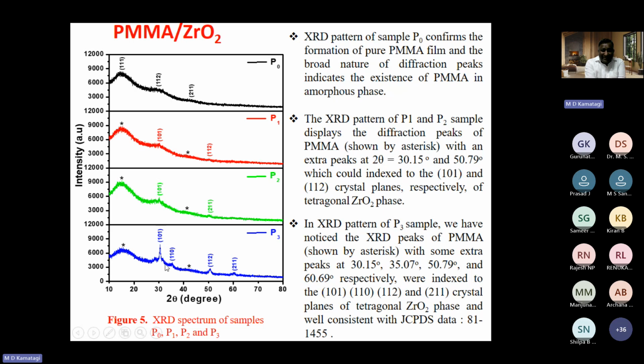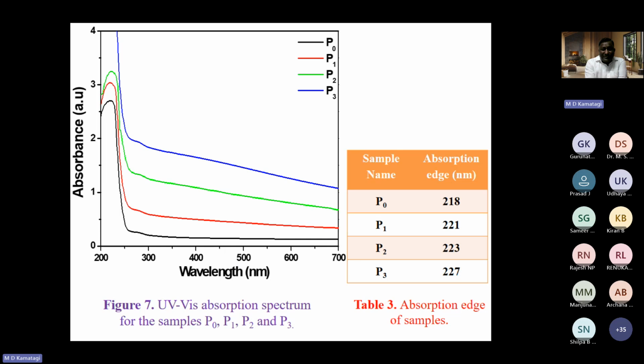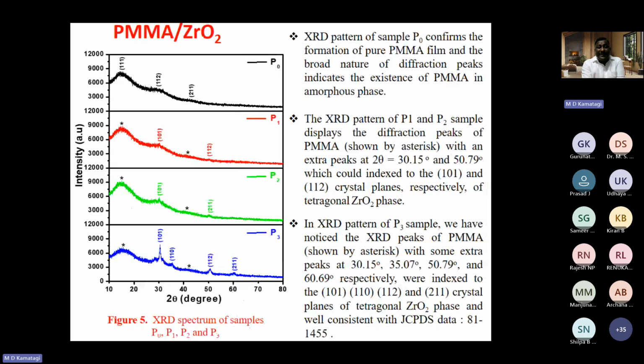For the highest doping, clearly we can see a crystalline peak, and other peaks also come. The extra peaks at 2 theta equal to 30, 35, 50 and 60 degrees were indexed to various planes of ZrO2, which are well consistent with the JCPDS data. This shows that by a simple solution casting method, we can introduce a nanomaterial into polymers or any other materials.